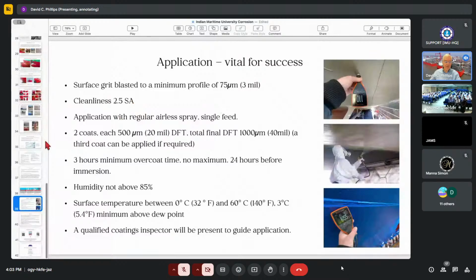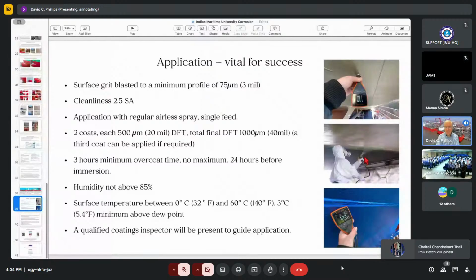The application is very simple. It's no special equipment. It's the normal shipyard paint spray equipment. It's a single nozzle, airless spray. There are some coatings, like for example, solvent-free epoxy, where you need to have two paint heads and they've got to be heated and the conditions are very important. It gets complicated. With this, it's very simple. You just use your regular single feed airless spray.